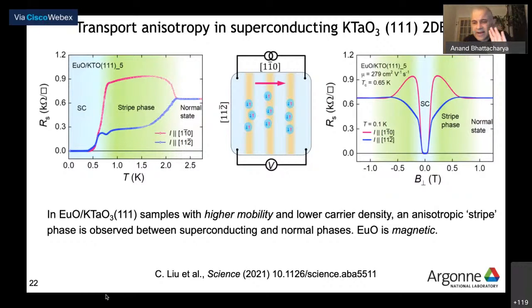So I'm somewhat familiar with this stuff. I used to work in a lab that did 2D superconductivity, a lot of it. And so I knew about this kind of physics a little bit. But what was really amazing was that depending on the direction of current, you would see this different physics. So the red curve is what you would find in a granular superconductor, where essentially what happens is that you kill the coupling between the grains, and then the normal electrons in the grains cannot hop anymore.